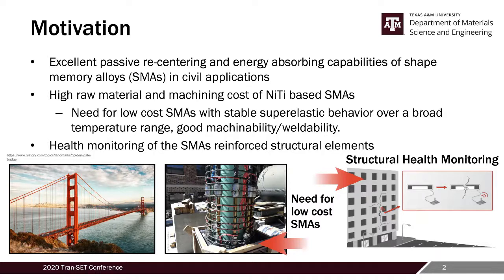So what we do in this work is to introduce a low-cost alternative of these SMAs, which is iron-based shape memory alloys. And what we want to do is to incorporate these materials into structures. And plus, there's this additional property of iron-based SMAs, which is that they can show magnetization change during deformation. So we want to use this property to monitor deformations in the structure. So we want to use this material as health monitoring elements in the structures.